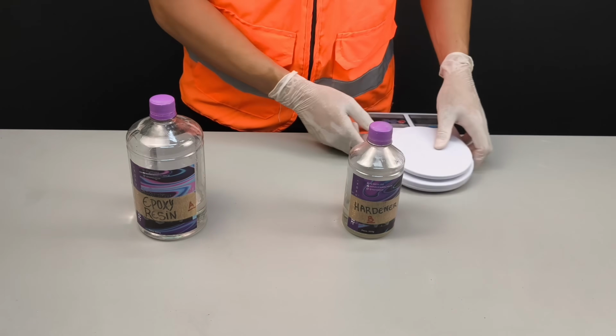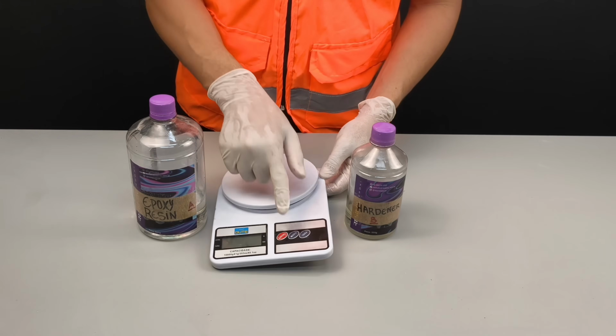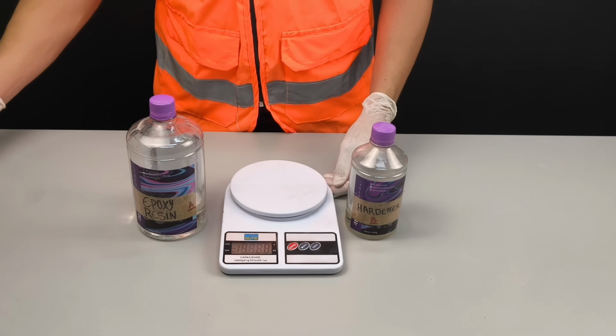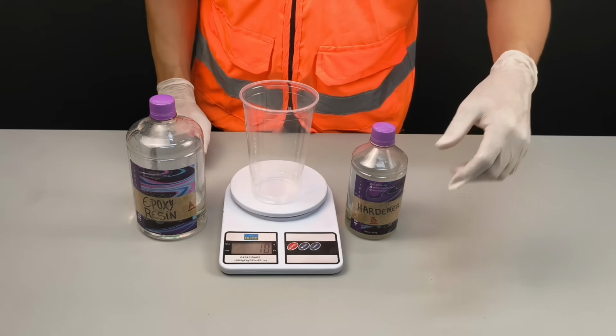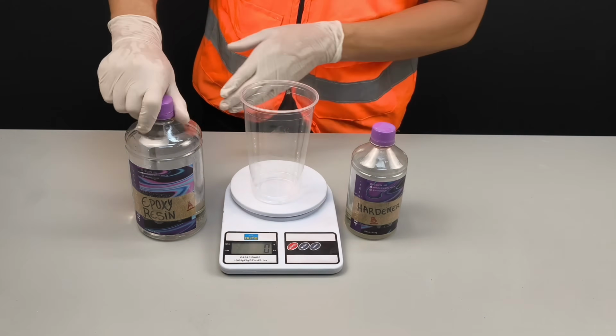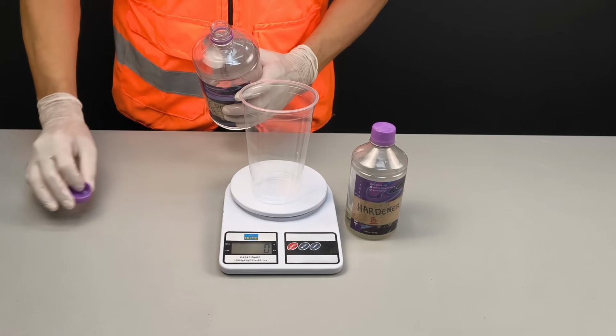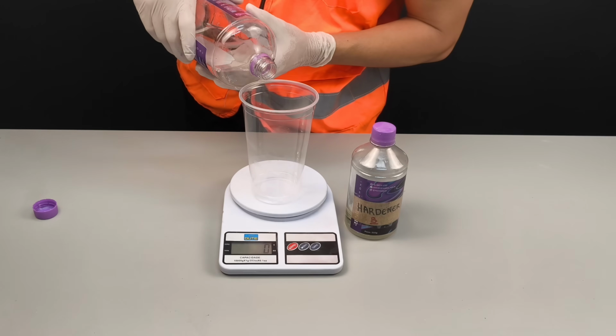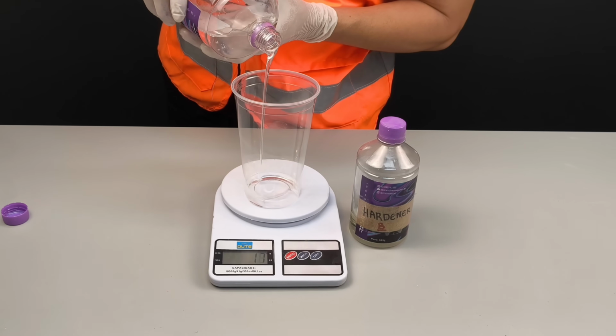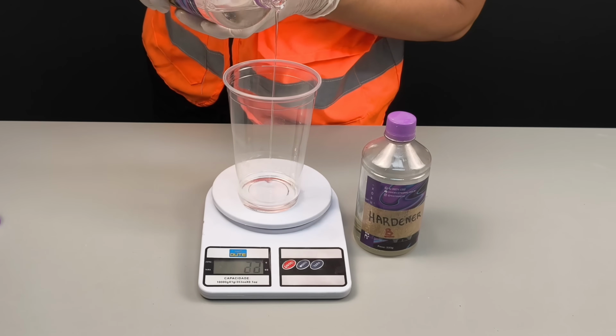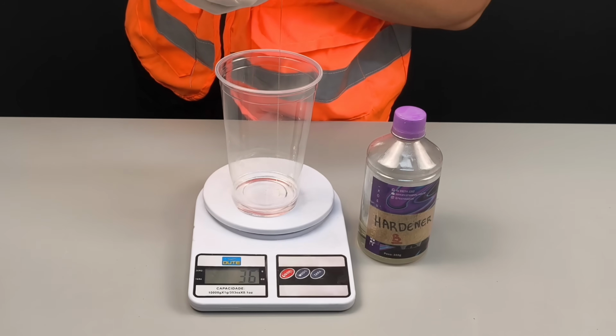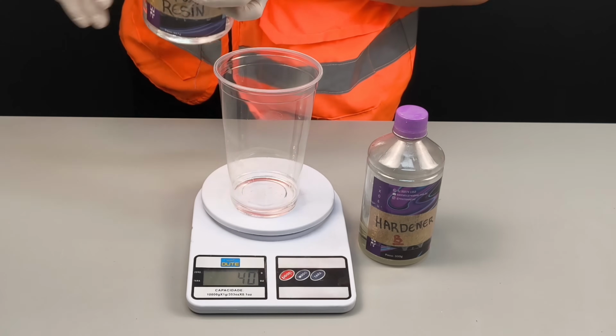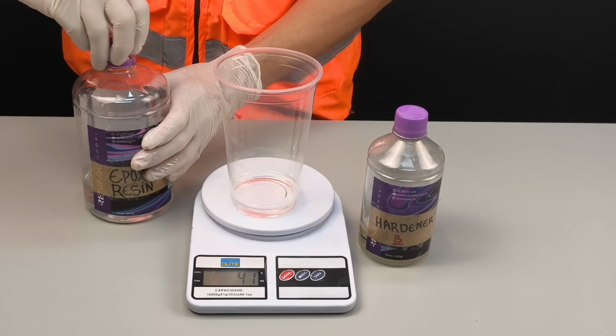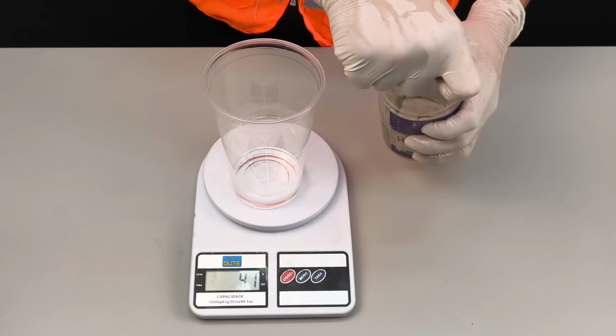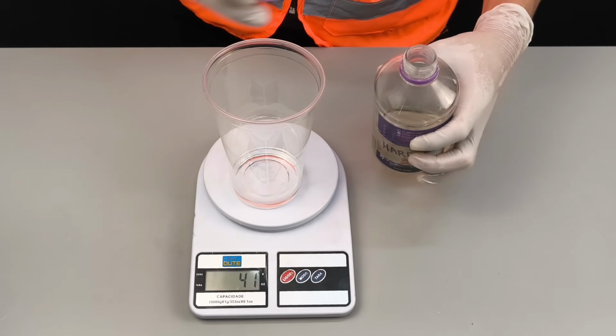To ensure accuracy, I use a precision scale following the exact 2-to-1 ratio, where the hardener equals 50% of the resin amount. Correct measurement is essential to achieve proper curing, strength, and clarity in the final result. After measuring, I mix thoroughly to achieve a uniform blend while avoiding excess air bubbles. This first layer of epoxy is responsible for sealing the entire surface, bonding the CD fragments and creating a stable, even base for the next finishing steps.